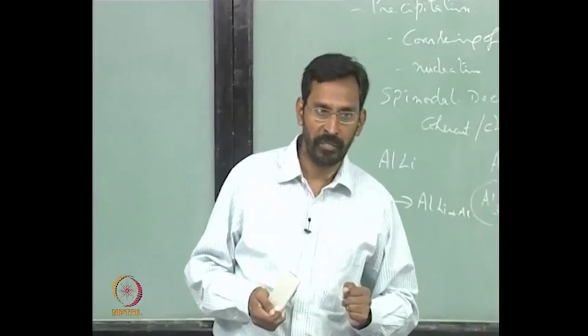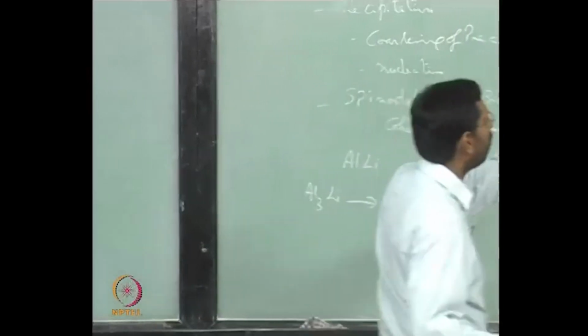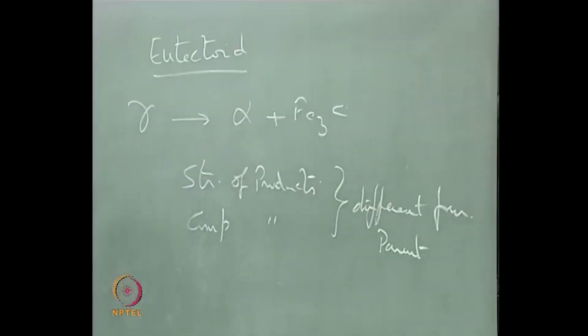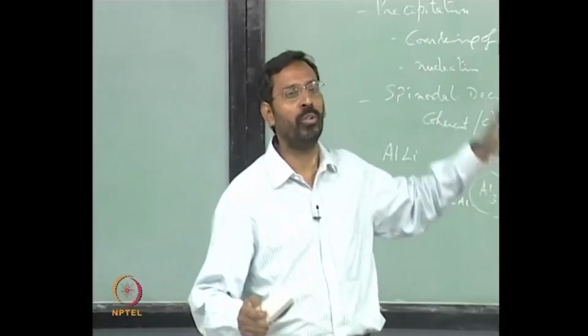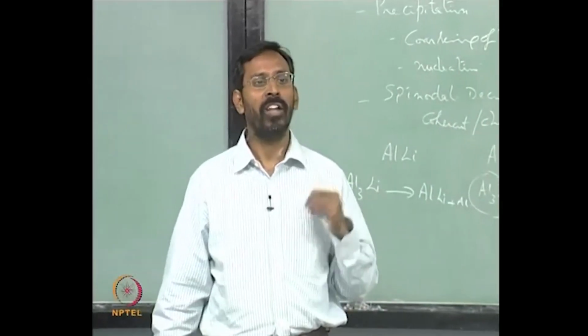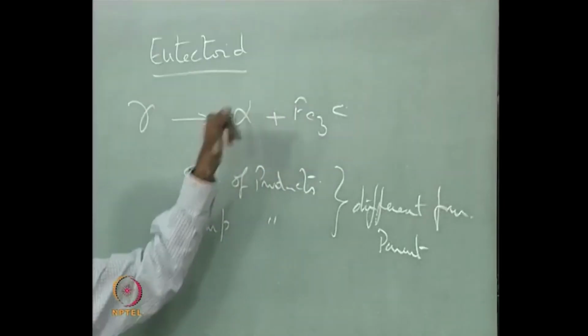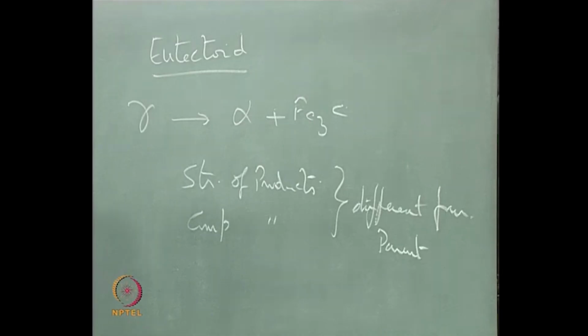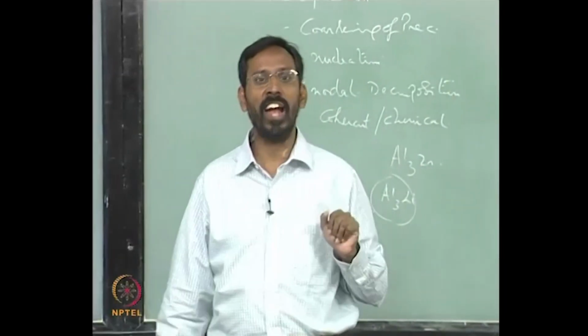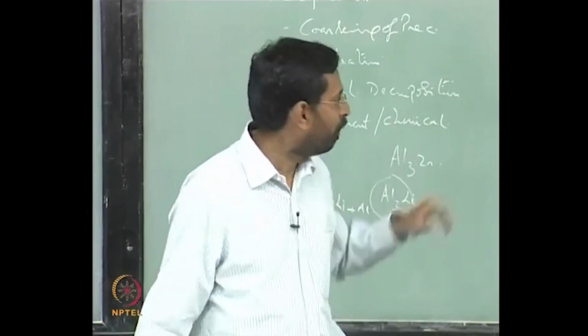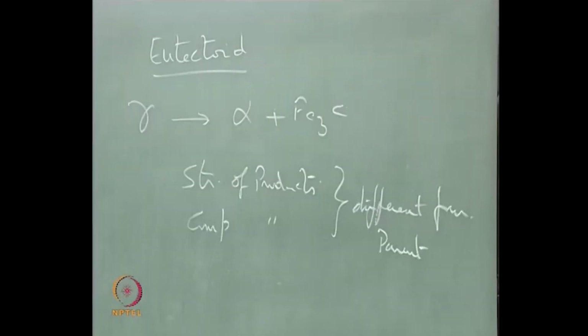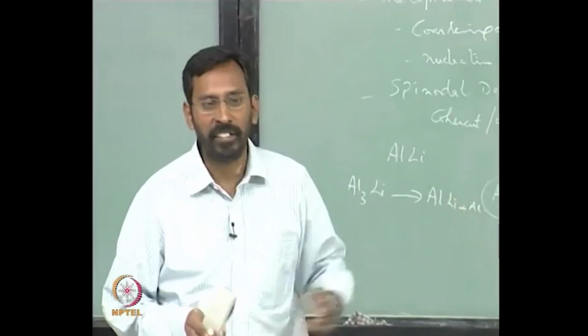Here you have no choice, here your phases are fixed, your eutectoid phases are fixed. So the product phases are fixed. Once the product phases are fixed, automatically their structures are fixed, their compositions are fixed. So as a result the system has no choice of choosing something else, so it has to go through only that process. If it has to go through that process, then the activation energy for such a process depends on what? Can we still change the activation energy for such a process? How do we change the activation energy? Can I reduce the activation energy for such a transformation?